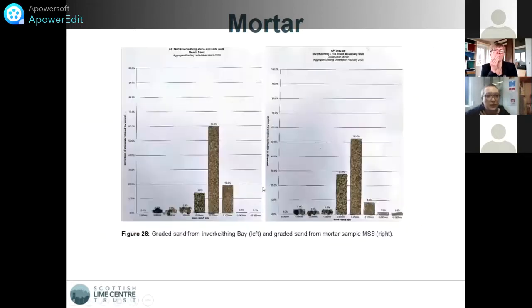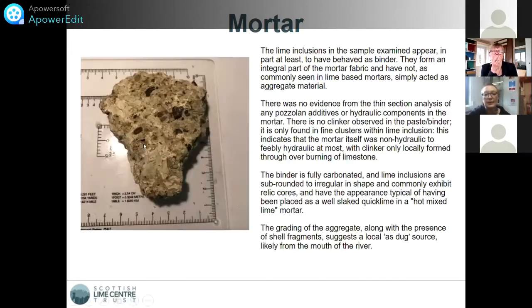And the binder was all fully carbonated, and the lime inclusions had a really irregular shape to them, and that normally would give the indication that it had been made as a quicklime in a hot mix style. And another thing that indicates that is the presence of things like shell fragments that we found.